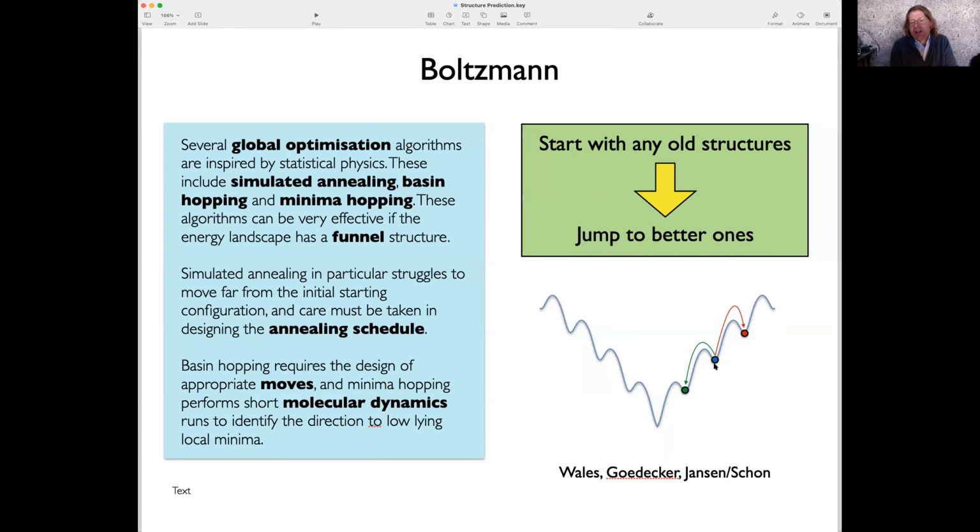You get your initial random structure, you relax it to a certain local minimum, and then you need to make a move. You need to go to a new place. And so you can do random moves. So you jump your structure, you re-relax it. Hopefully it moves to a new local minimum. And then you see, is the energy of this local minimum lower? If that energy is lower, then you take that result. That's good. I've made progress, bank that result.